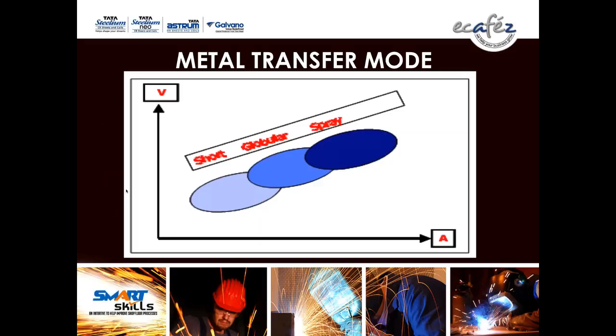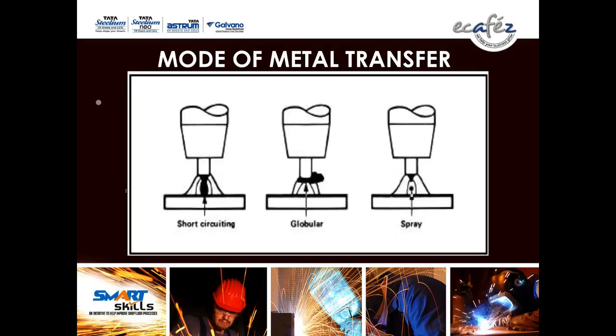When you increase the current and voltage from short circuit, globular transfer will be available. Then if you again increase the current and voltage, you can get the spray transfer. So see the pictorial view in mode of metal transfer: short circuiting transfer, globular transfer, and spray transfer. And spray transfer is the best transfer in the MIG process if you use argon CO2 shielding gas. So short circuiting is like this.